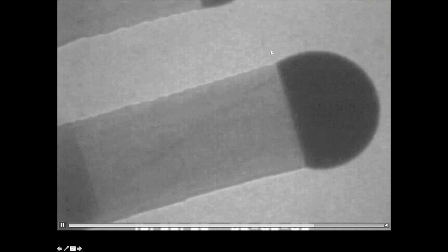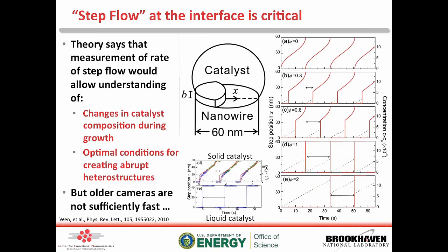Okay? So we're interested in lots of different aspects of this growth process, but in particular, because of the images I have, I'll show one small part of this. We've done things like look at step flow at the interface, and this is some work a couple years back where we described how step flow had some control over the compositional incorporation of different materials. We were in particular interested in creating these abrupt heterostructures, the ones where you can incorporate maybe a single layer or two of germanium in a silicon nanowire.